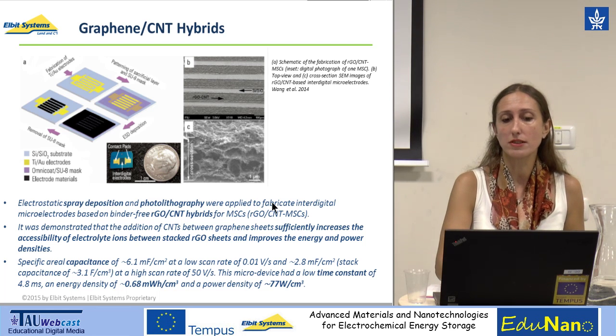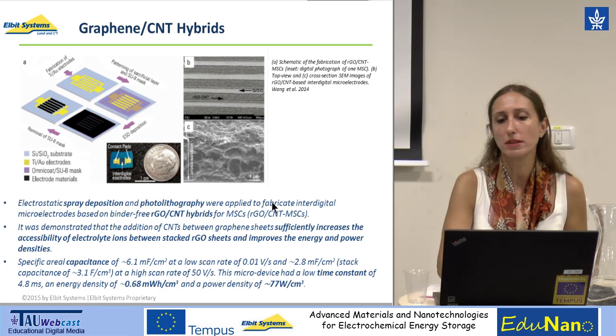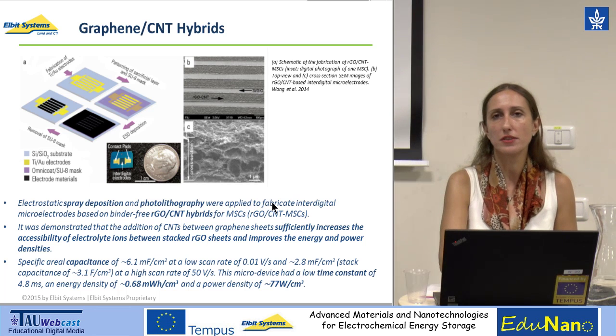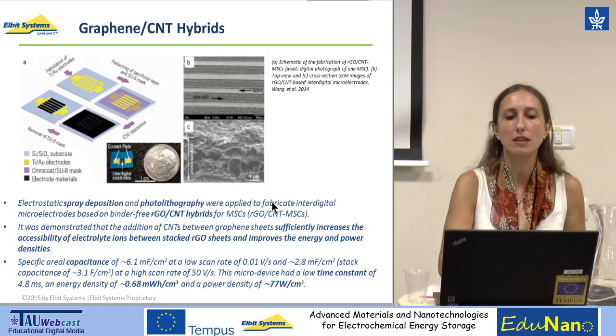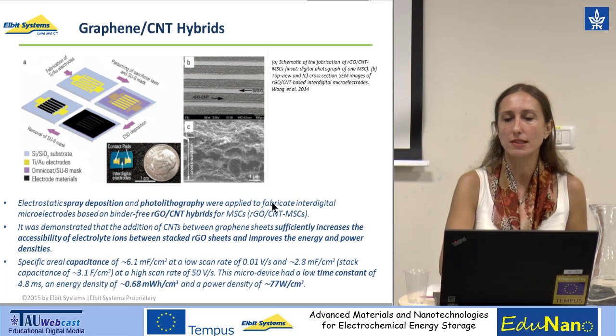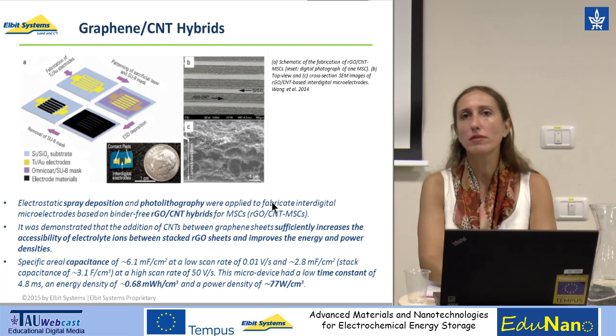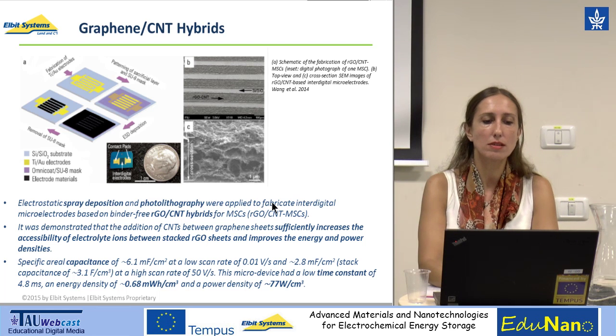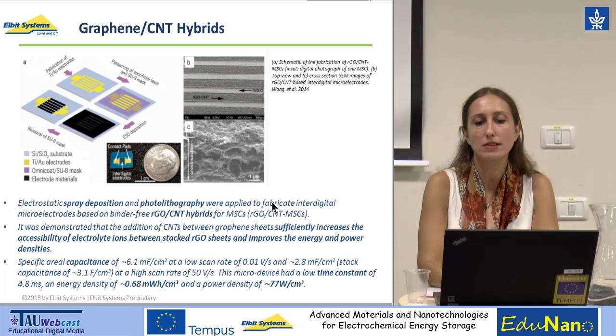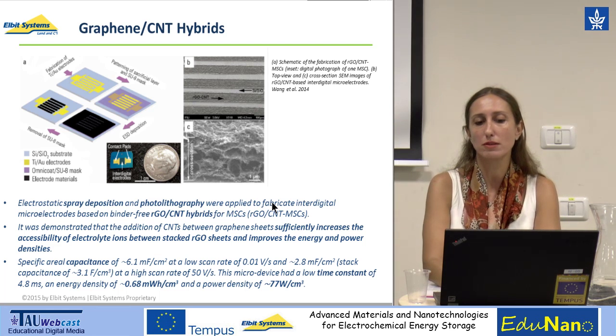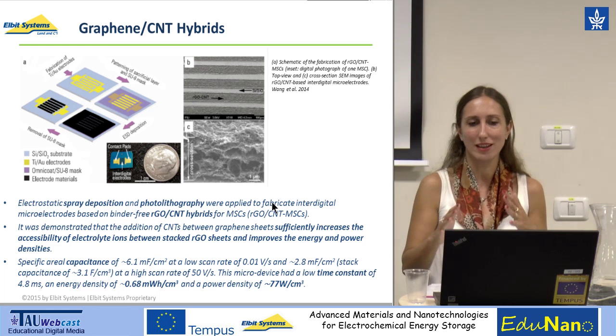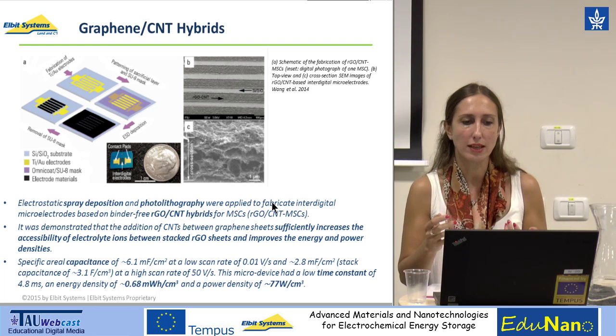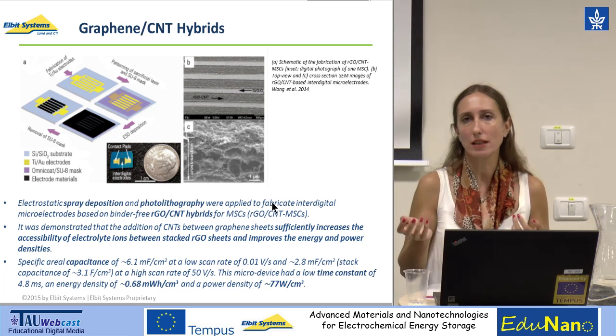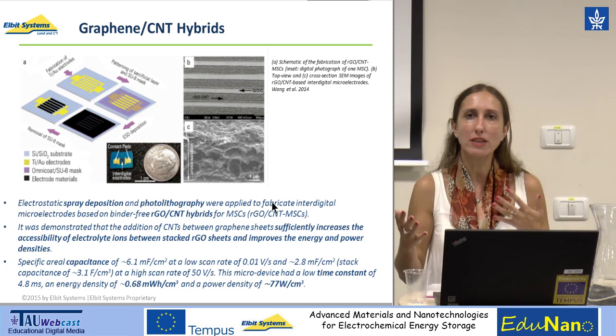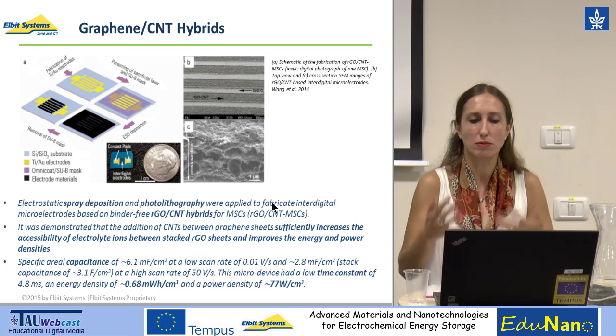What they did demonstrate is that the addition of the CNTs between the sheets of graphene sufficiently increased the accessibility of the electrolyte ions between the stacked RGO sheets, and in this way they improved the energy and power density. So the specific areal capacitance was 6.1 millifarad per square centimeter. Now we are talking about microelectrodes, so the range of farad is, of course, reduced.